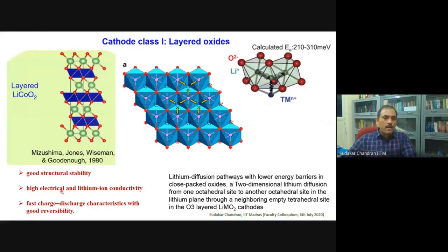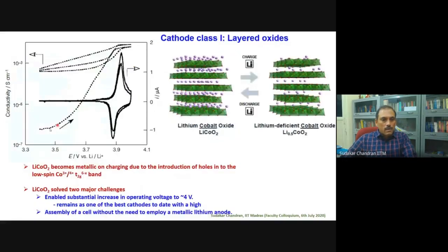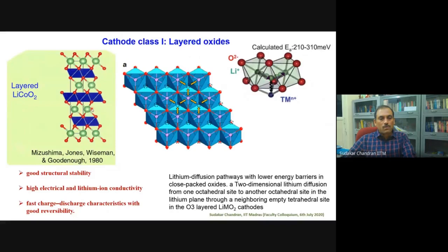It also exhibited very high electrical conductivity. So initially it exhibits an insulating character. The moment you remove lithium, it becomes metallic. So the metal insulator transition takes place in this compound, and it happens because of the introduction of holes into the t2g6 bands. So they are very good conductors. As such, you don't need to worry about how to extract the charges from these cathodes.